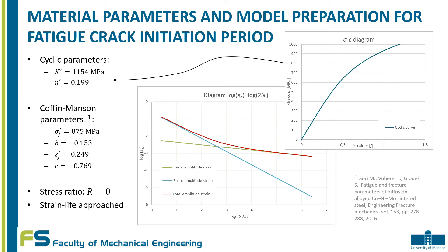The parameters of the given sintered steel were found in the previous work, in which only static material parameters and the fatigue strength exponent and coefficient were given. The cyclic curve parameters were determined on the basis of the Ramberg-Osgood equation. The fatigue ductility exponent and coefficient were also determined from the literature. The given diagrams show the material models used. Since fatigue-crack initiation is based on dynamic loading, the stress ratio was set to zero.